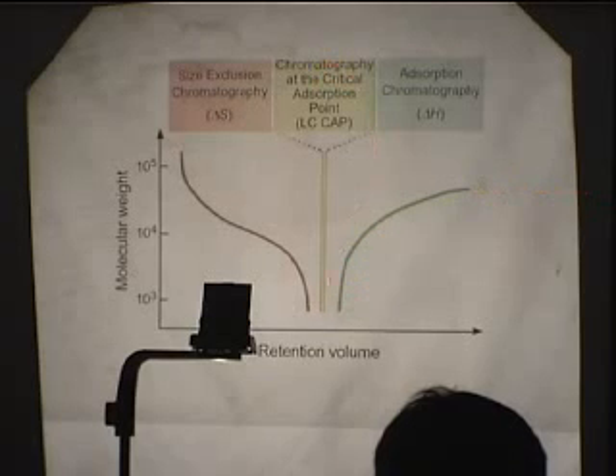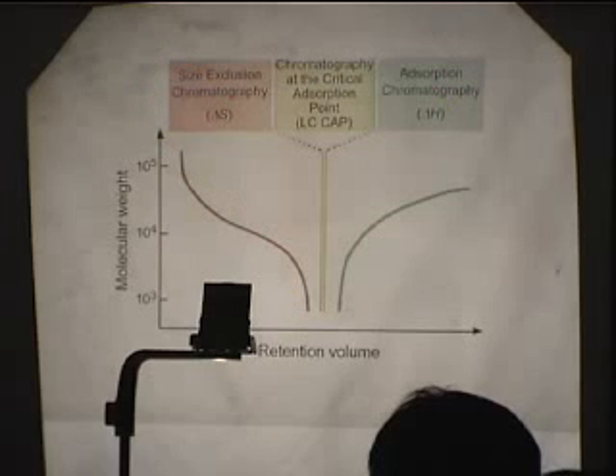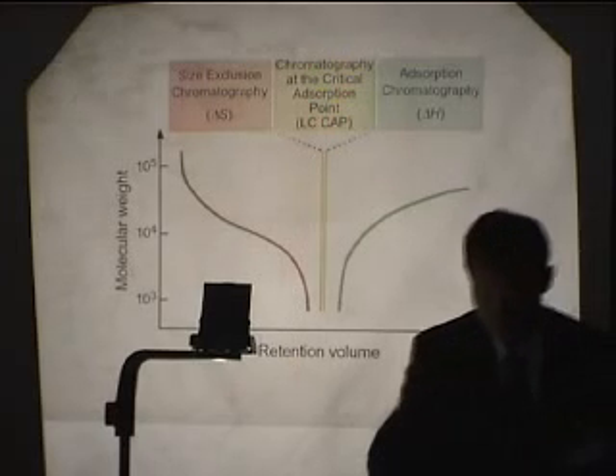At the critical adsorption point, where the size exclusion effect and the adsorption effect are balanced, all polymer molecules elute at the same retention volume, regardless of molecular weight. Accordingly, we can detect small changes of polymer structure such as tacticity by chromatography carried out at the critical adsorption point.